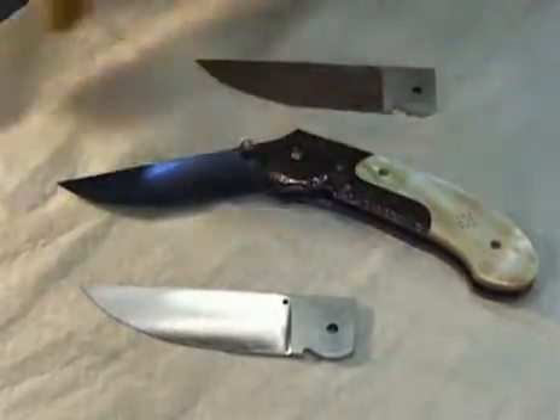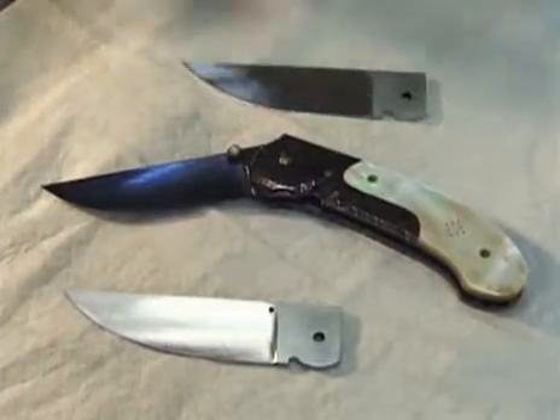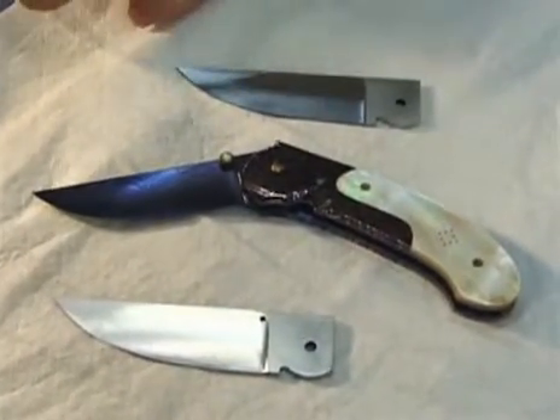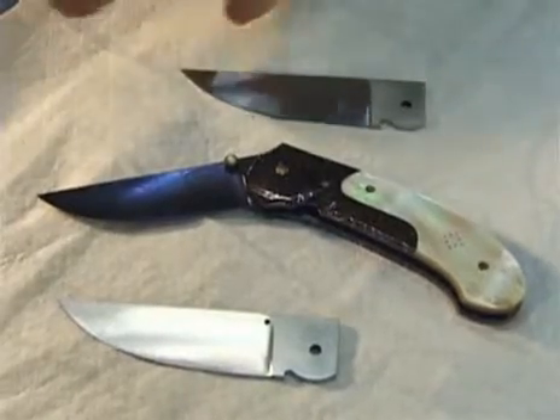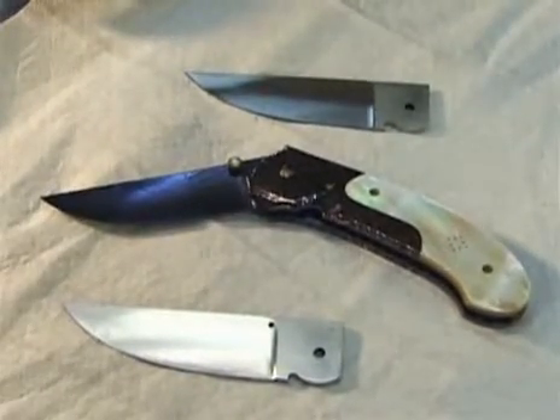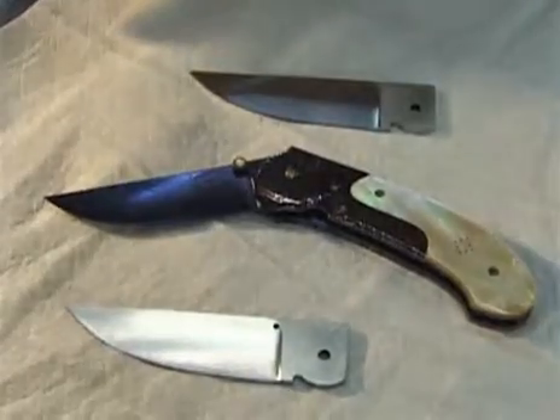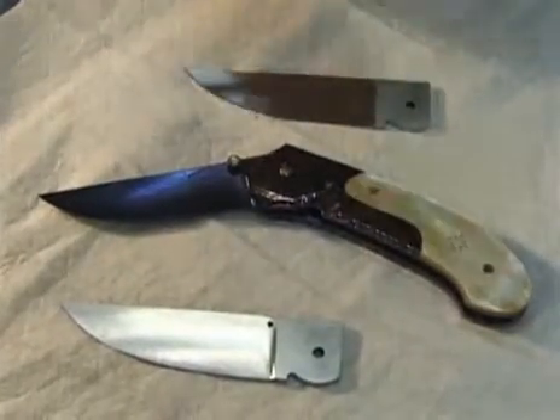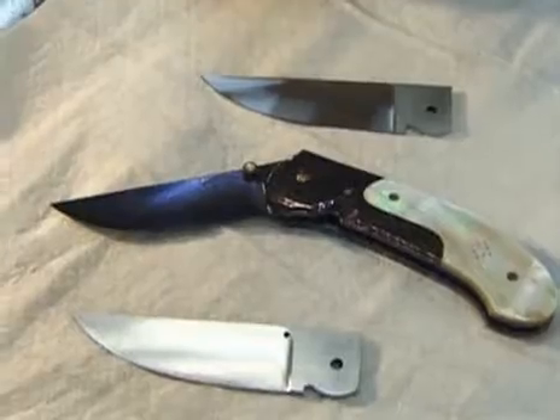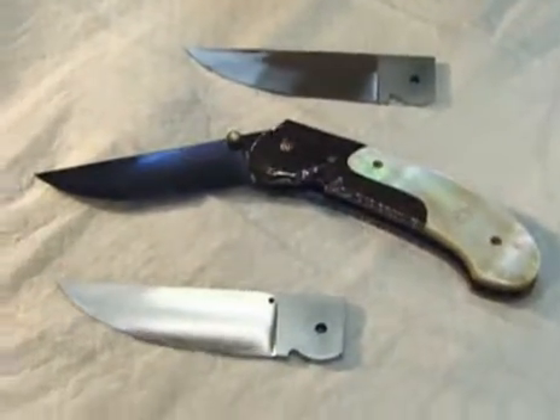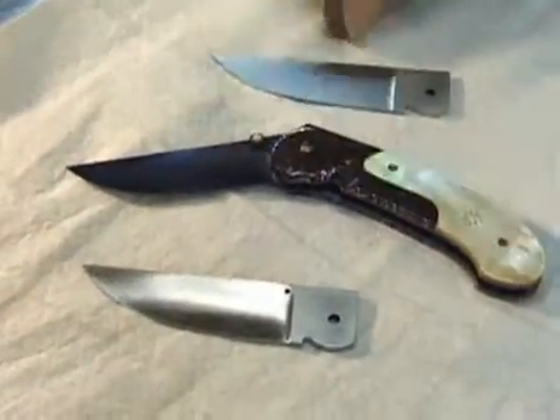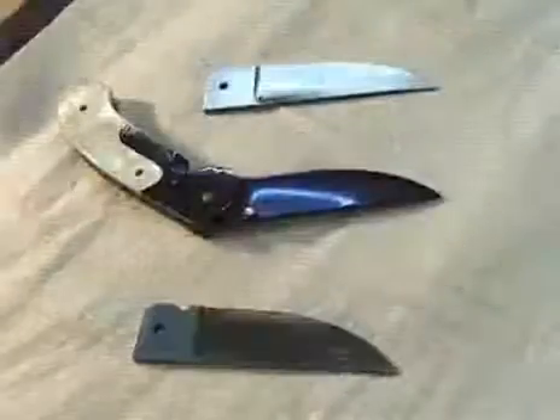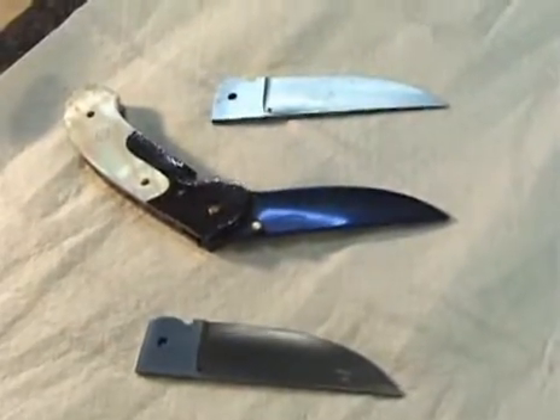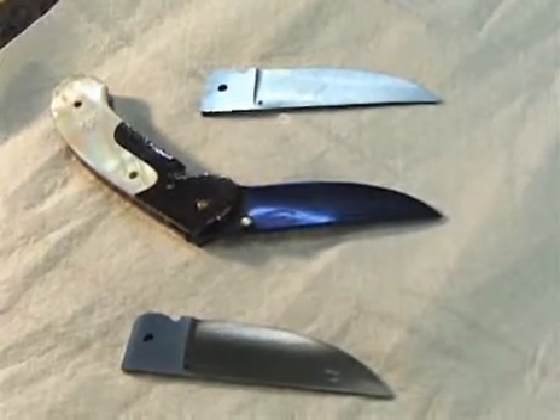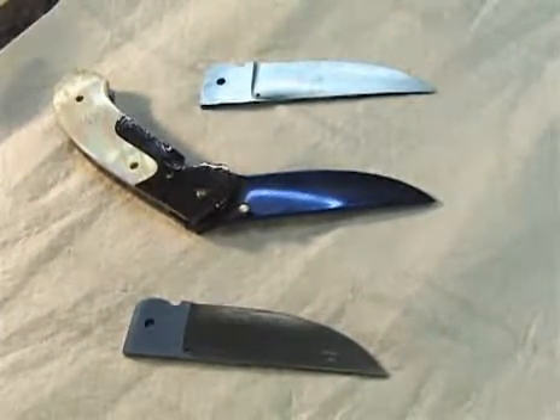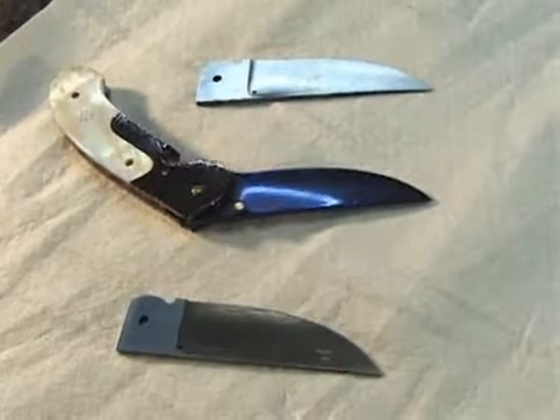but after I etch these, I've got several options. I can just etch them and leave them black, or I can hot blue them, which will be a dark gun, what we call a gun blue, or I can niter blue them, and I can get a variety of colors out of that Damascus by niter bluing it. This one just happened to, due to the steel, I got a real pretty blue out of it, but you can get some purples and greens and reds, and it's all based on the heat of your salts when you're niter bluing those.